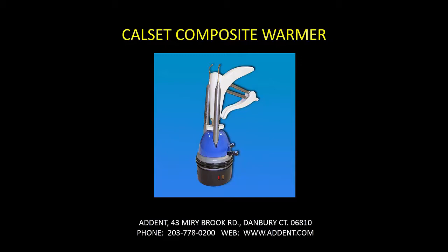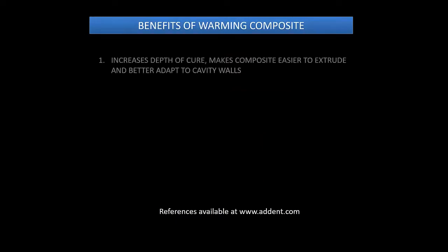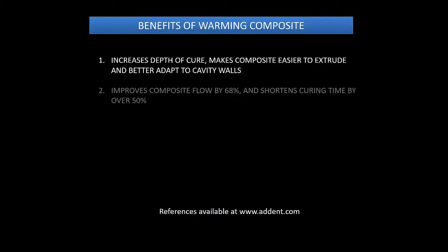And as I told you, I have product tests. And this is one that's new to me, dropped in my lap, and it's a composite warmer. And it's really a slick, neat little system. The benefits of warming composites are several things. Here you can increase the depth of cure because the composite's easier to extrude and it adapts better to the walls. And it improves the flow by almost 70%.